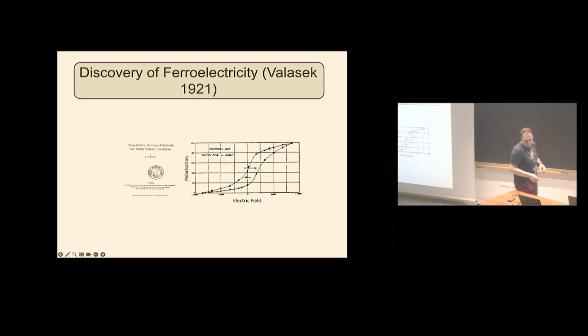And the product of the hysteresis really was that if you go to very large negative fields and then reduce the magnitude of the field towards 0, you end up with one particular value of polarization at the 0 field. But if you do the opposite and go to very high positive fields and then reduce the magnitude of the field down to 0 again from the other side, one ends up with a different value of the remnant polarization at 0 applied field.